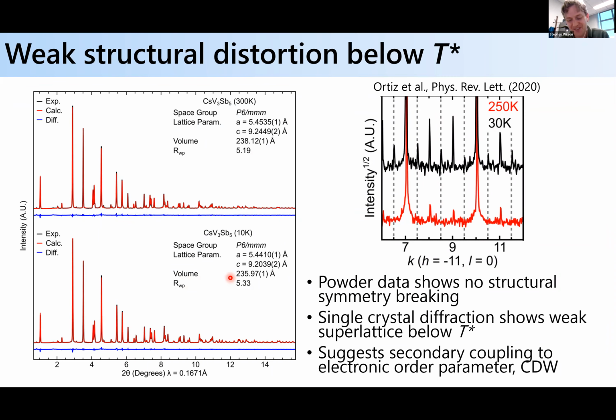We're getting close to doing that, and I'll try and motivate it in a moment. Because of COVID, we can't actually travel to these synchrotrons, and so we're reliant on people doing these measurements remotely, and these guys get swamped and have so much data that it takes them forever to provide reduced data for a structural refinement. And when you start talking about these very weak superlattice peaks that are 4 and 5 orders weaker than the primary, then we have to be very careful in terms of the normalization of the data and the structural refinement. So that's ongoing, to try and get a sharp structural refinement. But I'll motivate what we think it is in a few slides.